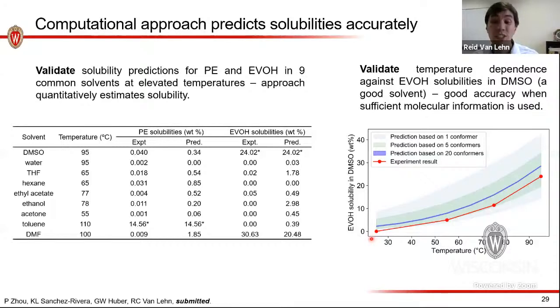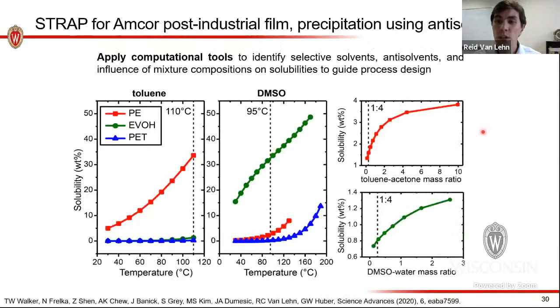We can also do this as a function of temperature, where again, we can validate computational predictions here in blue against experimental results in red. We see a slight overprediction, but all of the trends are the same, and that's really all we need to identify the best solvents. Okay, so now that we have these computational tools, we can start to design recycling processes for the STRAP process.